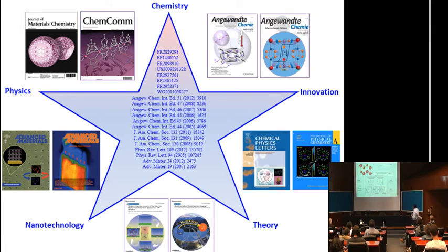As a function of the interaction between molecules, we can have different behavior. When we have weak interaction between molecules, we have quite gradual and sometimes incomplete transition. On the other hand, when you have strong interaction between molecules, it's possible to have abrupt transition and hysteresis loop and even transition in different steps. I would like to illustrate these different behaviors by showing you examples of spin crossover materials.